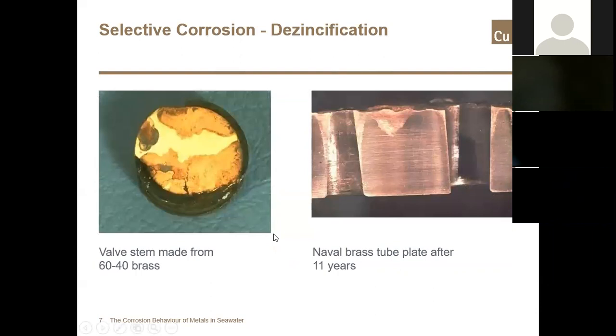So just to go on from the selective phase attack from the cast iron side of things, it's not a phenomenon that's limited to cast irons. On screen you can see a valve stem made from 60/40 brass that has shown signs of dezincification. Obviously the material was specified incorrectly and has failed in operation, and it's due to the zinc phase corroding preferentially, as it wasn't as noble as the copper.